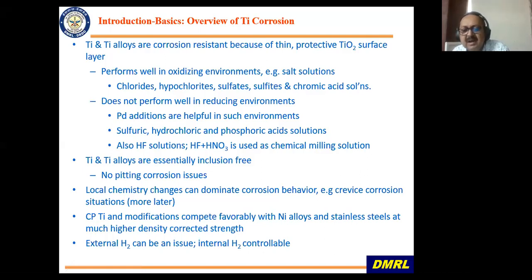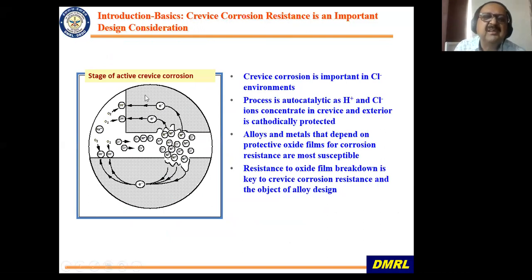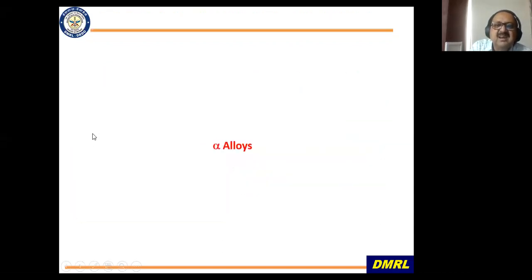It takes in a lot of hydrogen, and this is where I'm showing this crevice corrosion. Crevice corrosion is important. If there is an application that you are designing using titanium alloys, and it is in a certain amount of fluid, and there is close contact with, let's say, riveting or bolting, and it is a closed process where you have chloride environments, this is autocatalytic. It disturbs this oxide layer in the closed spaces where the gap is small, and outside is protected, but in these closed crevices it starts eating away the oxide, and you can have problems of crevice corrosion because of the breakup of the oxide layers. So I will now talk about different alloy systems, and then finish off.